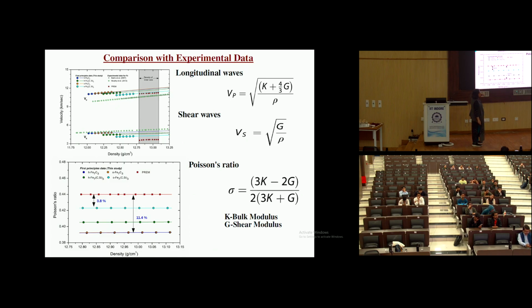What is being calculated is the sound velocities, which can be two different ones. You can have a longitudinal wave, you can have a shear wave, and you can also calculate the Poisson's ratio. You can see all of them are related to nothing but the bulk modulus and shear modulus. And you have to calculate it, of course, at the Earth's condition of pressure and temperature, which we did. Then we also plotted it as a function of density. These square points are the experimental data.